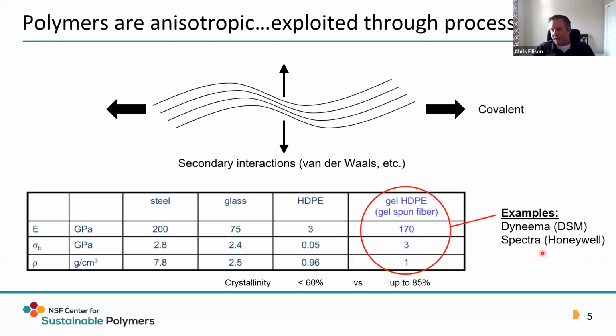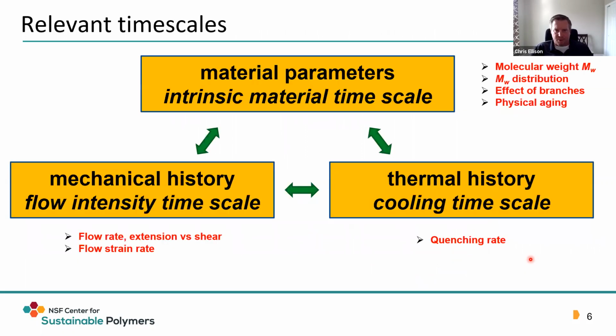However, if you process it by gel spun fiber process, you can actually make fibers that are competitive with steel, but have almost 8 times lower density. This is a result of alignment of polymer chains. It's sold as several different commercial products, one by DSM called Dyneema, and the other by Honeywell called Spectra.